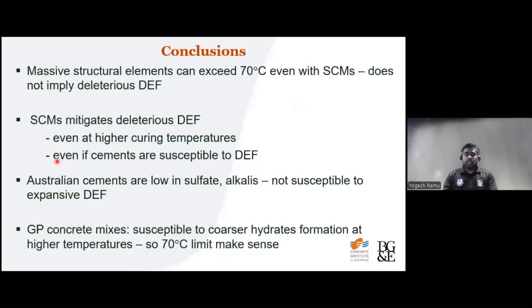In general, in theory, SCMs have low DEF risk because of low sulfate and alkalis in them. And it also makes a lot of sense to restrict plain GP concrete mixes to 70 degrees Celsius, as they are susceptible to ettringite precipitation, and also susceptible to coarser hydrate formation, which can reduce the mechanical performance like compressive strength, and can lead to highly permeable concrete. So it makes a lot of sense to restrict the temperature to 70 degrees Celsius.